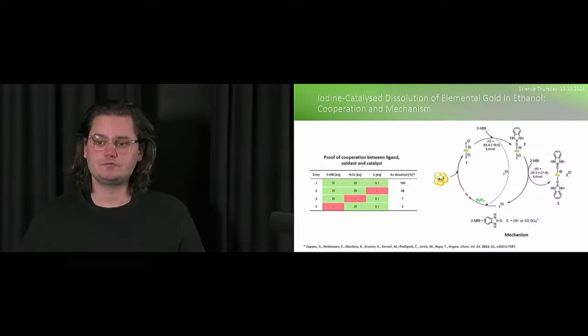cation. So if you check the catalytic cycle, first one molecule of 2-mercaptobenzimidazole comes and substitutes the iodide on the gold plus center. Then the second molecule comes and forms this stable complex 3 that dissolves the gold. And the expelled iodides can be reoxidized by hydrogen peroxide back to elemental iodine that can again start the catalytic cycle by dissolving more gold.